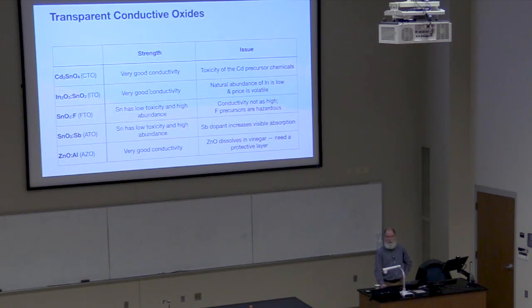Indium tin oxide, very good conductivity. This is used all over the place. I'll show you some pictures later. The actual abundance of indium is not great, and the price is volatile. So we looked at that and ruled it out. Fluorine-doped tin oxide: tin has low toxicity compared to cadmium, and high abundance compared to indium. It's not as good conductivity-wise, but it's pretty good. Tin doped with antimony is similar, but that antimony dopant gives a little absorption, a little purple color. So you don't want that in the solar cell. It might be good elsewhere, but not in the solar cell.